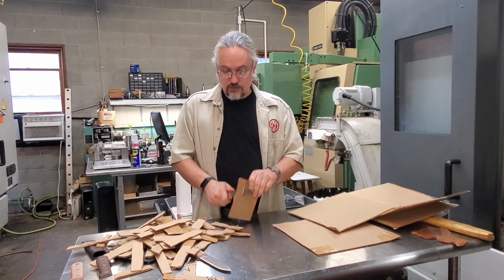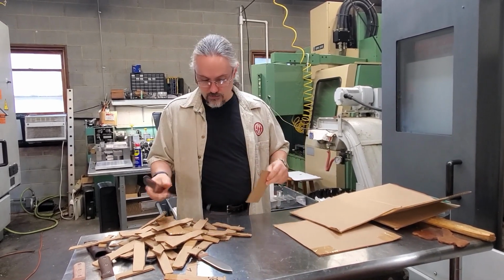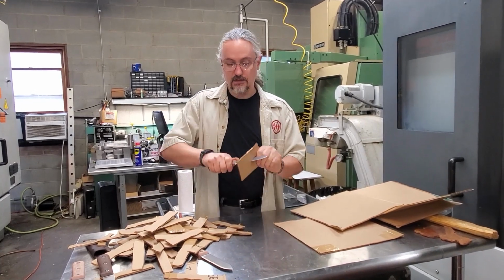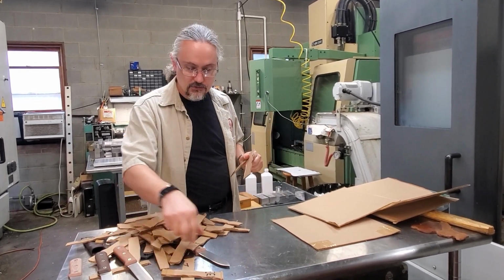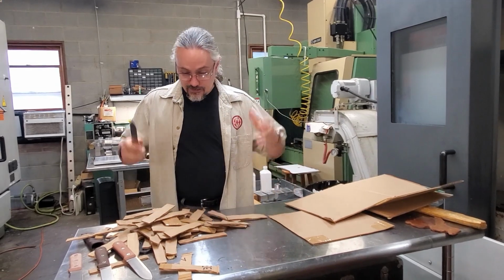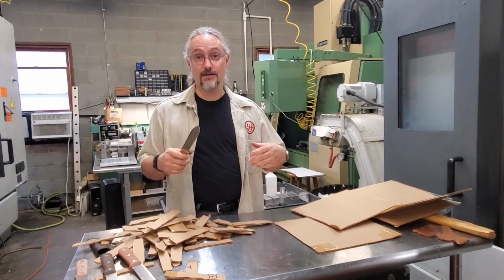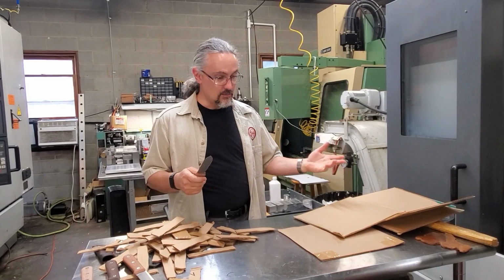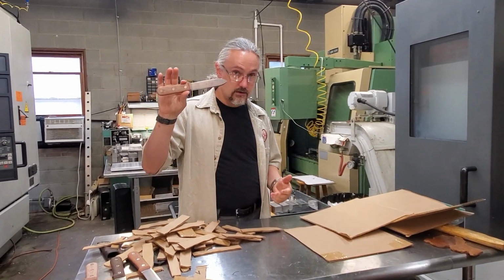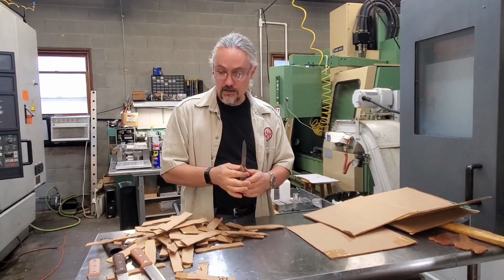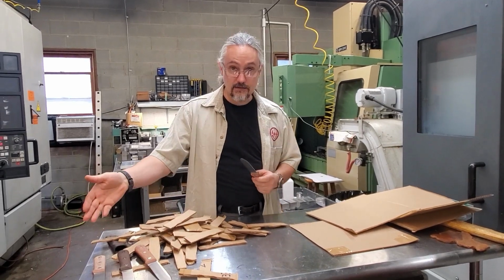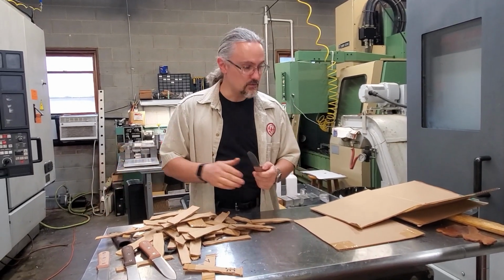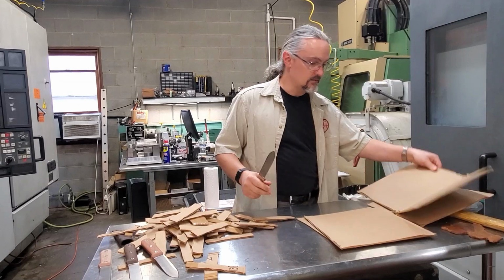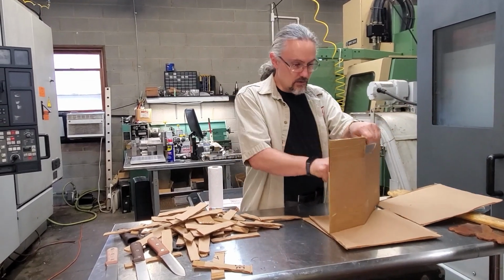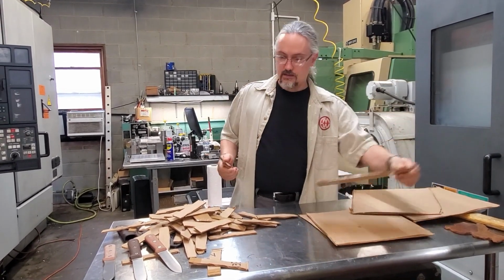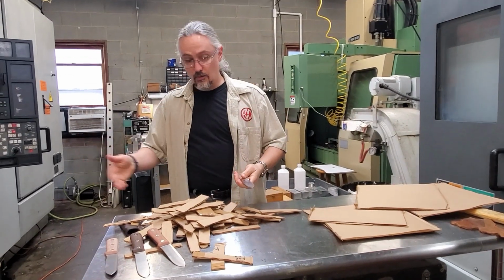So the way you can tell if your heat treat did what you wanted it to do, or if you're developing a heat treat and you can see whether or not one heat treat is working better than another, is to do what I'm doing here, which is cut repeatable media with your knife that you're wanting to evaluate and compare it against other knives as standards. And so this is a non-quantitative approach that will give you this is better than that, but it won't give you a number.